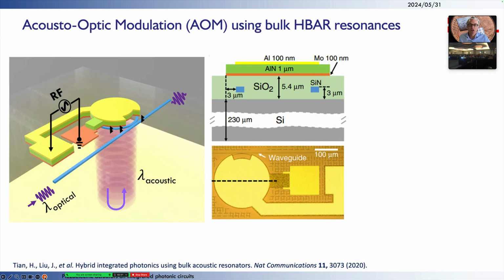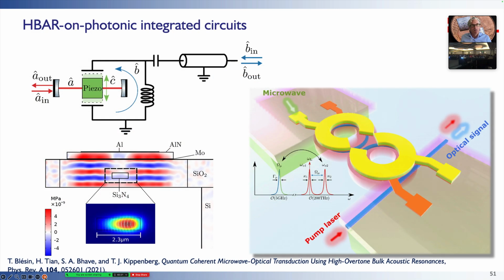And so just to give you one example of what can be achieved. We can also use the H-bar modes of the stack itself, which have a free spectral range, in our case, of about 17 megahertz. And we can use those to create what we like to call piezoelectric optomechanics, where we have an incoming microwave field that is driving via the piezoelectric effect an acoustic wave, which in itself is coupled to optical modes, in this case of a doublet resonator. And so what we can achieve here is, if we drive, for instance, this piezoelectric actuator at 5 gigahertz, we couple and we drive this doublet.